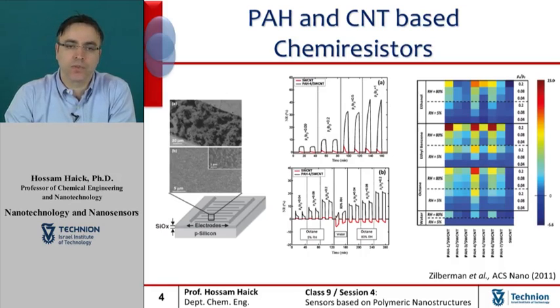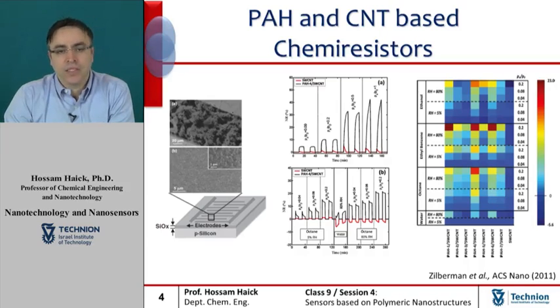In many cases, the higher the relative humidity in the mixture, the higher the improvement as compared to the pristine single-walled carbon nanotubes. In some cases, such as for the PAH5 and single-wall carbon nanotube sensor, the sensitivity to the polar volatile organic compounds, such as in the cases of ethylbenzene and ethanol, increases with the increase in the relative humidity. This is indicated by the enhanced color variation when volatile organic compound concentrations are increased in a background of 80% relative humidity compared to the 5% relative humidity.